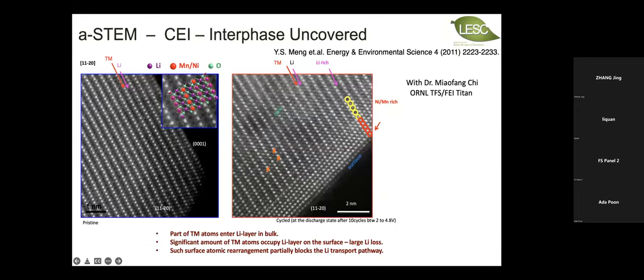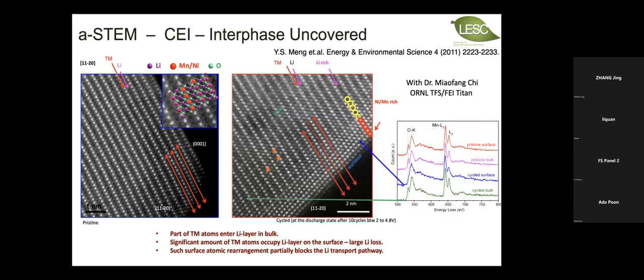A good example to show you is that electron microscopy was previously very successfully applied in studying the cathode electrolyte interface. This work is almost 11 years old, and it really revealed the power of electron microscopy, how it helps us reveal the surface 4 to 5 atomic layer changes, and the insights gained more than 10 years ago for the cathode materials really helped us to understand the high voltage stability of those cathode materials.